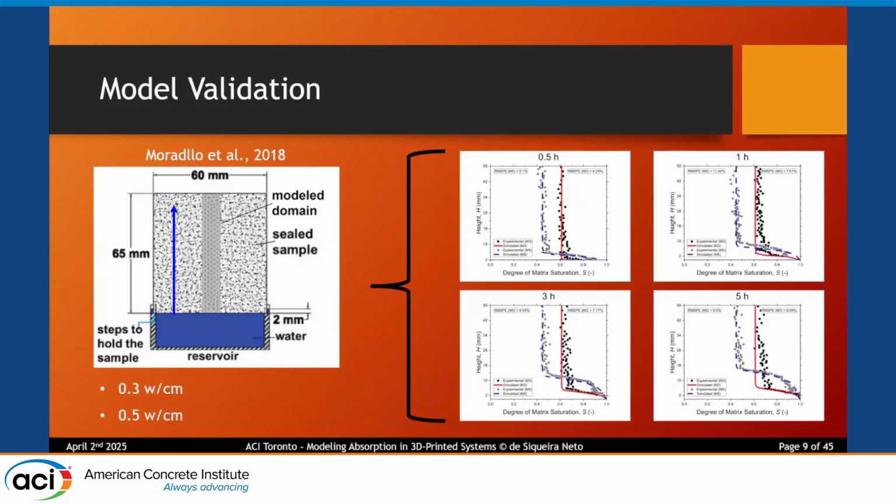So we have validated this model by comparing the simulation predictions to a couple of fluid absorption experiments that our group did a few years ago with two mortars with different water to cement ratios. And as you can see on the four plots on the right, the red and blue curves corresponding to the simulation predictions match the scattered experimental data really well.